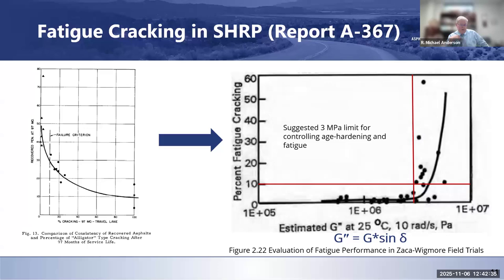So my guess, and I'm not going to say this is definite, is they're looking at the entirety of probably as much as a 2 to 4 inch layer that they would be recovering. And you're going to see definitely higher stiffnesses closer to the surface than further down. That's why, when we're doing forensic analysis, you probably get a good representation of how the material ages overall by doing the combined amount. But if you wanted just to look at near surface aging, we'll typically cut the top half inch or thereabouts, or top 12 millimeters of the surface, just to see what near surface aging looks like.